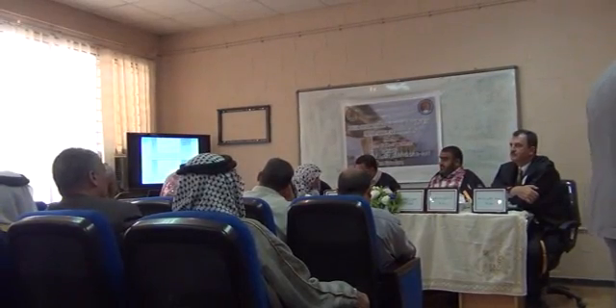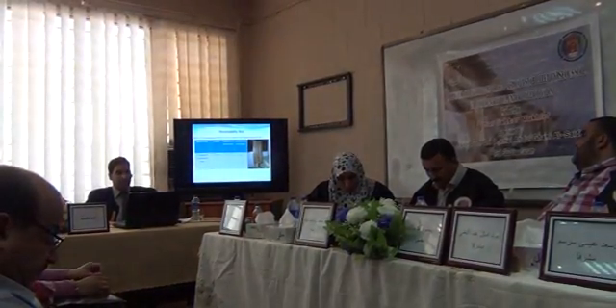This figure shows the stress-horizontal displacement relationship for stabilized soil with emulsion in soaking and out-of-soaking conditions. This figure shows the stress-horizontal displacement relationship for stabilized soil with cutback in soaking and out-of-soaking conditions. This figure shows the stabilized soil specimen by emulsion under direct shear test in out-of-soaking condition. Permeability test results for non-stabilized and stabilized soil: for pure soil k = 7.5 × 10⁻⁷ cm/s; for stabilized soil with emulsion, k approaches zero; for stabilized soil with cutback, similarly very low.